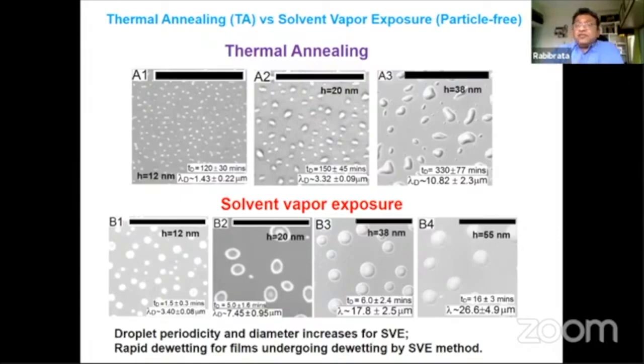In contrast, you do solvent vapor exposure. So it's half a minute, 5 minutes, 6 minutes, 16 minutes, and you can dewet a film all the way up to 55 nanometer. That's what we checked. We could have gone up to 80 nanometer, 90 nanometer. There is no end to it. We limited our investigation up to this range. And the same old belief, well, solvent molecules are penetrating, reducing the viscosity.